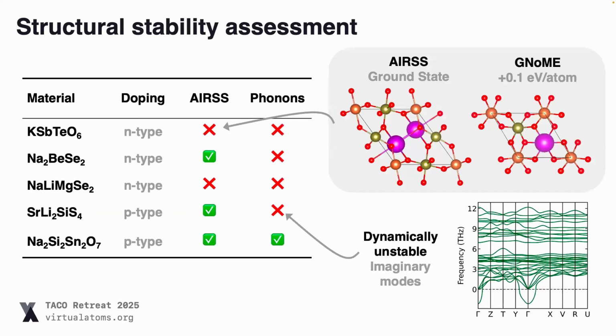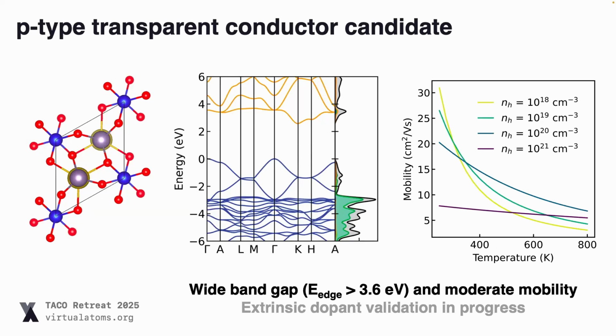It's this sodium, silicon, tin, oxygen material. This structure is already known. The lead version is known, and there's another A site cation, but the structure type is already known. This is a p-type candidate. It's got this hexagonal symmetry. What's very nice when you look at it is this band structure has a very disperse valence band, and so the effective masses are very low.